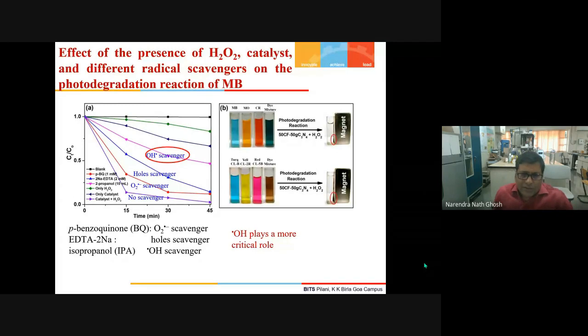Now, first of all, on the right hand side, I was first advocating about the magnetically separable catalyst. Here you can see two things. One, the colored solutions at the top: methylene blue, methyl orange, congo red and the mixture of the dyes. When we do the photocatalysis reaction with the composite of 50 graphitic carbon nitride and 50 cobalt ferrite, with hydrogen peroxide as a sacrificial agent, we saw that the color of the solution becomes colorless. And now you can see that we stuck one permanent magnet at the side of the cuvette and all the catalysts are accumulated there. Similarly, below are the different colored solutions of the industrial dyes, and we show that ultimately a colorless solution is produced.